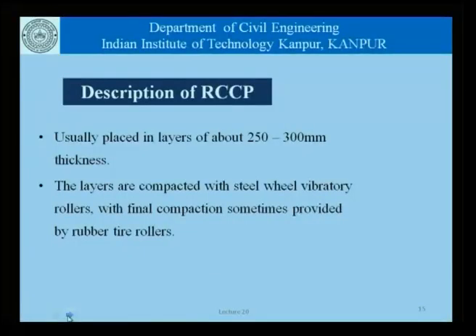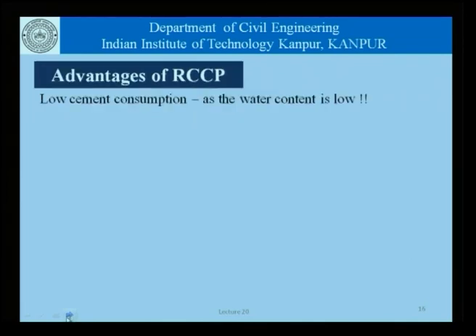Layer thickness is related to several parameters, including the size of the aggregate and the compactability of the concrete, which depends on the type of roller being used and the effectiveness of the roller in compacting the concrete. The layers are compacted with steel vibratory rollers, with final compaction sometimes provided by rubber tyre rollers.